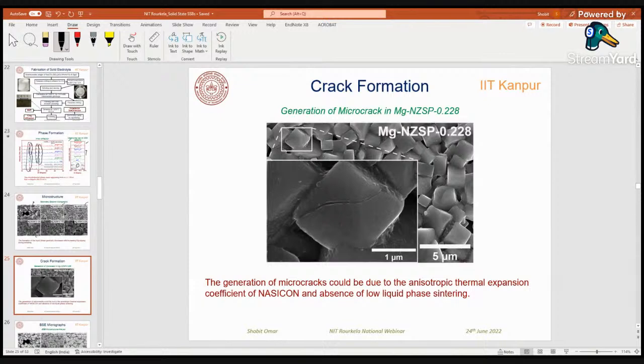However, as you go to higher magnesium content composition, you can find intragrain cracks present inside this material. We also observe some cracks along the grain boundary. This is detrimental to the conductivity of this material. We feel that this is happening because of the anisotropic thermal expansion, and also because of the absence of liquid phase. Because the liquid phase provides some cushion, and these cracks are not generated in lower magnesium content material.